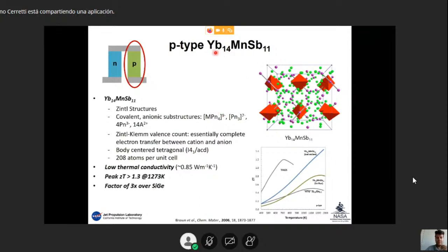On the P-type, we work on ytterbium-14 manganese antimony 11. This is a material that I mainly focused on in the past 2 years. It has an extremely complex structure; the unit cell has 208 atoms. That's huge, but the fact that it has all these atoms and these weird features guarantees extremely low thermal conductivity. It is one of the lowest thermal conductivities registered for thermoelectric materials. It has a peak ZT of about 1.3 at 1273 K, which is a 3 times improvement compared to the P-type silicon germanium previously used in the RTGs.